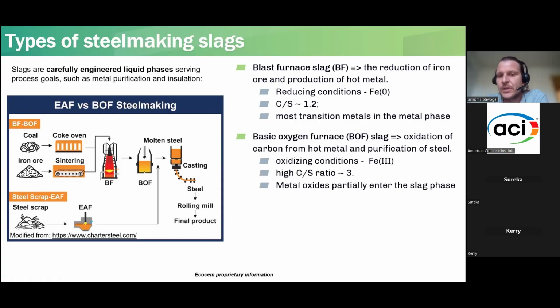This changes a bit already in basic oxygen furnace slags, because you blow in oxygen to oxidize the carbon out of the steel. You reach oxidizing conditions, and the iron at the output of the furnace in the slag is mostly iron 3. So you have some transition metals, including iron, including heavy metal. And the other big difference is that the calcium-silicon ratio is very high, around 3.